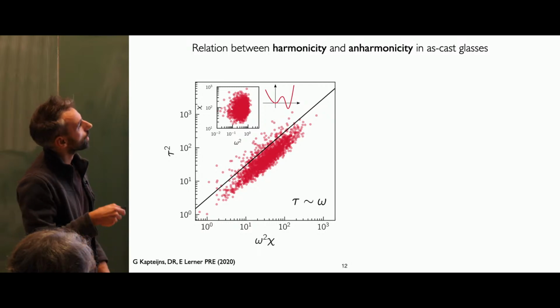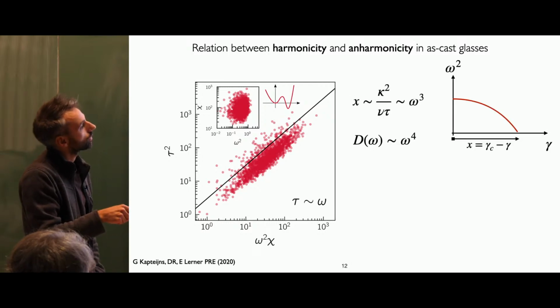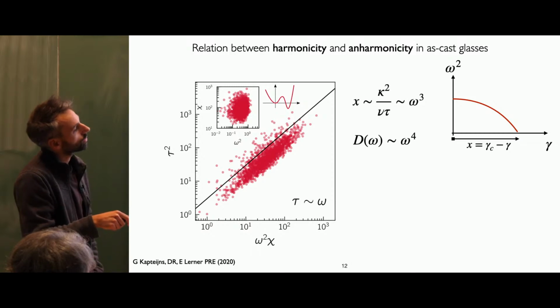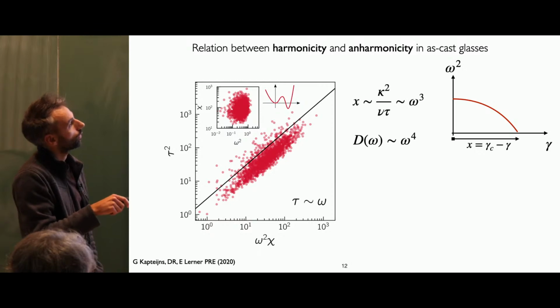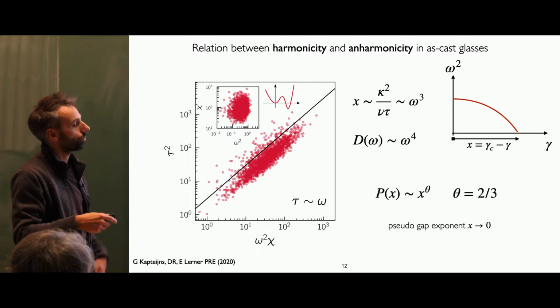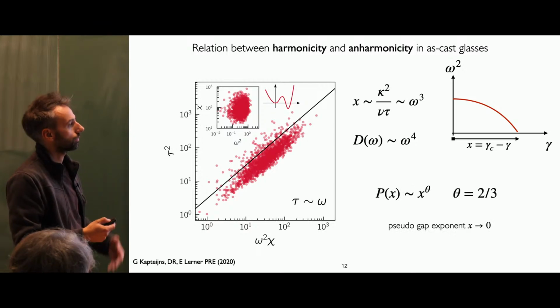And that was interesting at a quantitative level because we know that the strain distance to an instability, so x, which will be just the critical strain minus the strain, should scale for small distance as the stiffness squared divided by tau. So if you have a relation like this, it gives you a relation between frequency and distance to threshold, the local yield stress. And since we know how the frequency scales in this asymptotic regime, that gives us a prediction, for example, of how the local yield stress in a glass should scale.